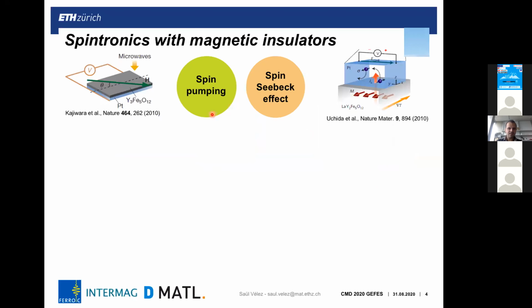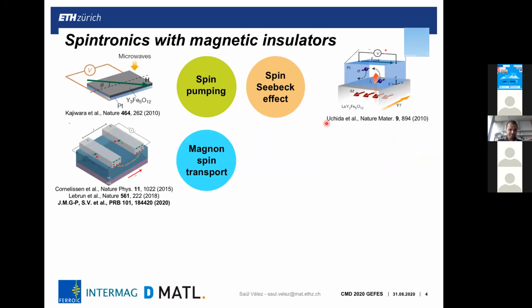There have been several realizations of spintronic devices using magnetic insulators coupled to heavy metal layers. For instance, by exciting the ferromagnetic resonance of a magnetic insulator, you can pump spins into a heavy metal layer and detect them by the inverse spin Hall effect. You can also excite spin currents through the interface by applying a transverse thermal gradient across the interface.